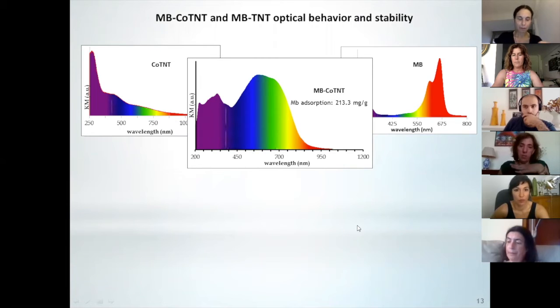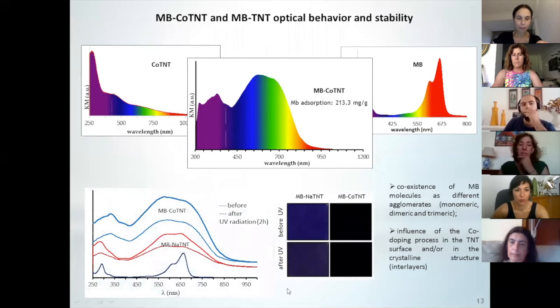In this case, we decide to test how stable these structures are. And as you can see here, we put it as a solid under UV radiation. Oh, sorry, this is before and after. And as you can see here, they are stable under radiation. And if we look at the photos of the powder, we can see that, in fact, when we are working with the cobalt titanate nanotubes, these samples are very, very stable, even under radiation.